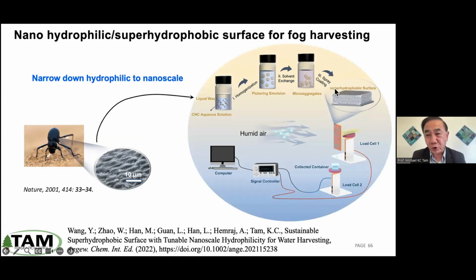So now the surface is super hydrophobic. We then subject humid air to the surface and monitor the water droplet capture. We measure the weight of this plate versus time. And when the water droplet becomes large enough, gravity will take it down. We measure another weight, total amount of water collected.